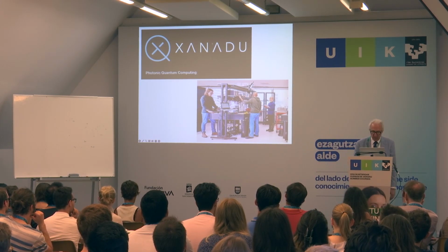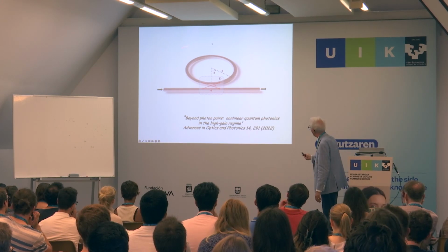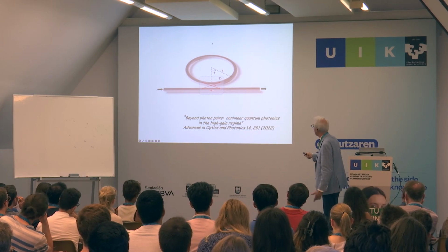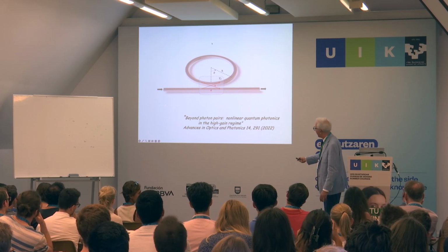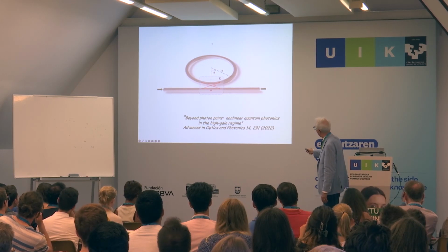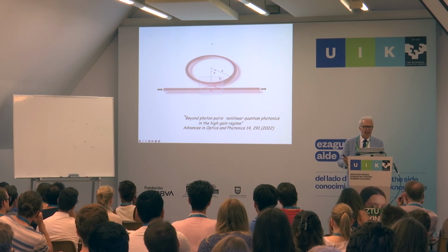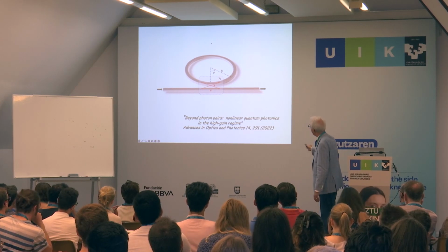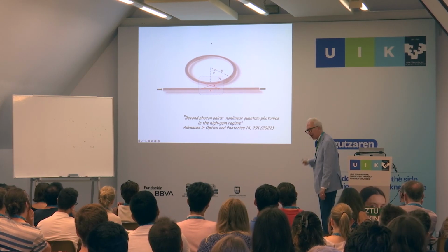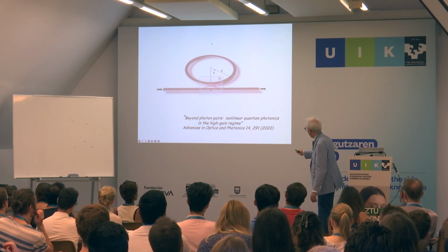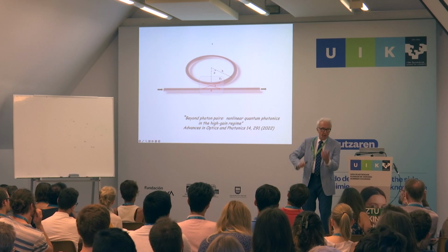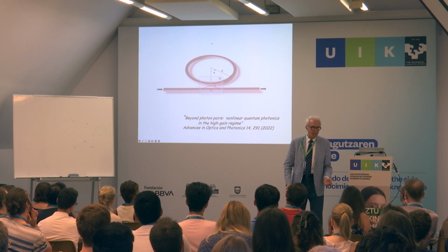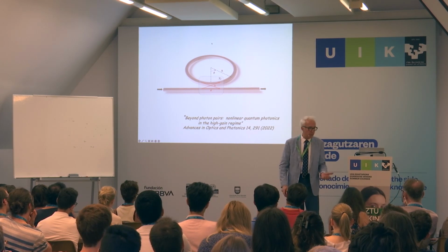And what's going on is when one's using things like this, these ring resonators, okay? So I've got a channel waveguide here. This is maybe 10 microns in diameter, okay? Light can evanescently couple into this ring, okay? And it's like a photon hotel, right? The photons can check in. They can stay in the hotel for some time. Then they can check out, okay? But if they're at a resonant frequency, the intensity is going to be very high in this ring, and that will help you generate your entangled photons, your squeezed states, okay?